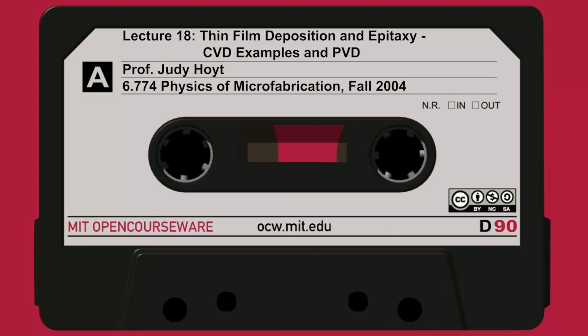And then the low pressure is maintained by a vacuum pump. So this is not an open tube furnace. The mouth of the furnace where the wafers come in and out is actually sealed with an O-ring, so you can pull a vacuum. In typical depositions, polysilicon is deposited on an oxide, maybe, or on an oxide with silicon windows. It's a non-selective process, so it goes over the entire wafer on all structures.